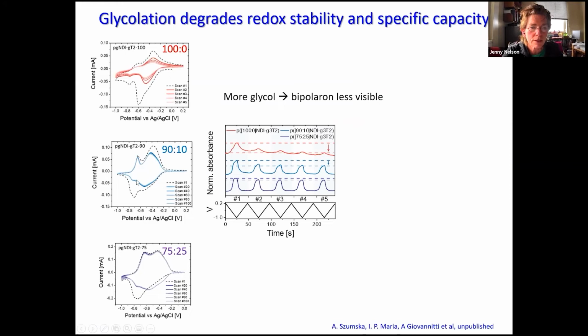And you can see from the CV scans here that as you go through subsequent cycles, there is really quite a loss in performance of the fully glycolated polymer compared to the ones which have only 10 or 20, 25% of the glycol chains replaced with alkyl chains. We could probe this also by looking at the absorbance by the bipolaron. During successive cycles, the totally glycolated polymer loses its bipolaron absorption relatively quickly, whilst the partially alkylated polymers manage to maintain their absorbance over successive cycles.